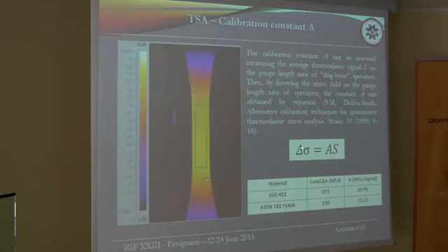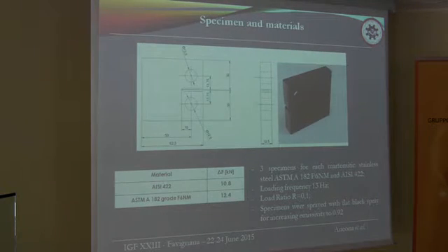In fact, knowing the stress field in this area, it's possible through this equation, and knowing the thermoelastic signal S, to evaluate the calibration constant A. These are the values that we found for the two martensitic stainless steels. So we investigated 3 CT specimens for each material according to standard ASTM E647. The loading frequency of the test